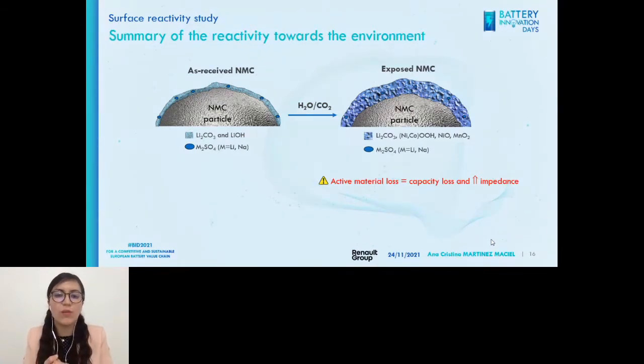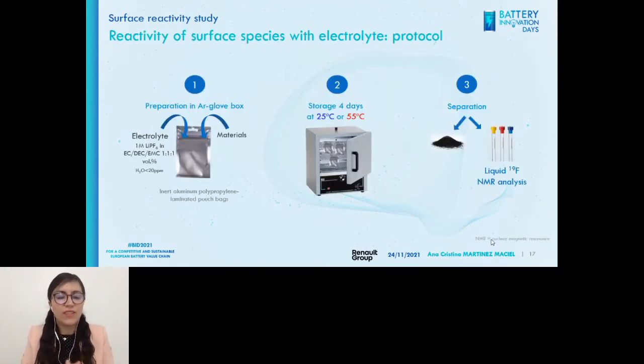So with this information, what we wanted to see now is the effect of the surface species in a battery. So for that, what we did was to artificially store the materials, either the NMCs as received or after exposure, or the pure materials - carbonates, hydroxides, or oxides - with electrolyte in a pouch bag. Then store these at low or high temperatures that are correspondent to what a car will attain, and then separate the powder from the electrolyte and analyze the electrolyte with NMR, nuclear magnetic resonance of fluorine.